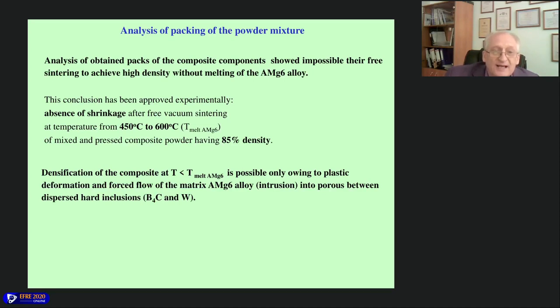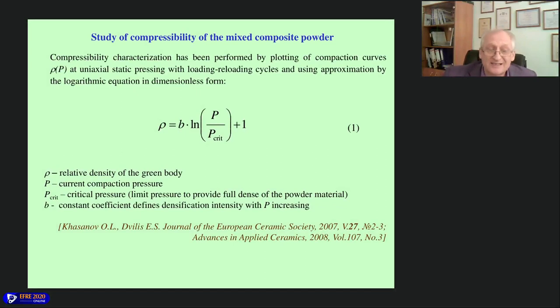Densification of the composite at a temperature lower than the melting point of the aluminum magnesium alloy is possible only owing to plastic deformation and forced flow of the matrix aluminum magnesium alloy into pores between dispersed hard inclusions, highly refractory inclusions such as boron carbide and tungsten. For modeling of such a sintering process, we used a special logarithmic equation of dimensionless form, taking into account the compaction pressure during sintering.